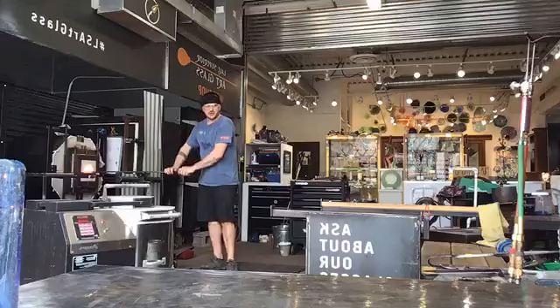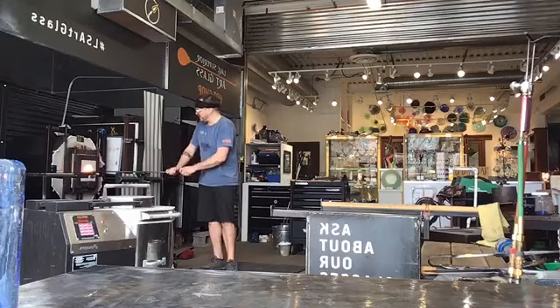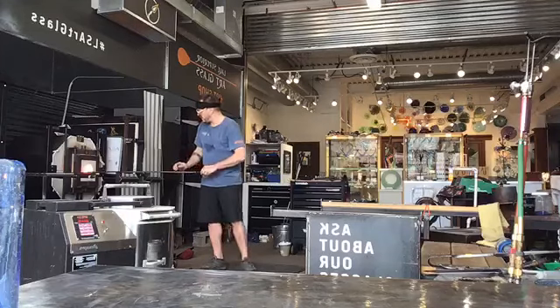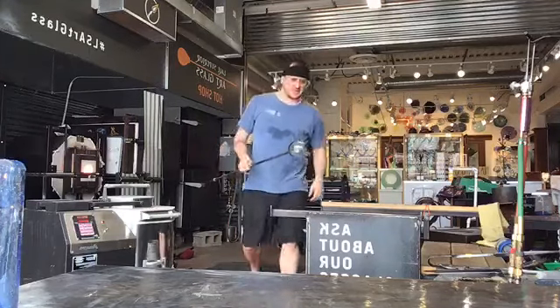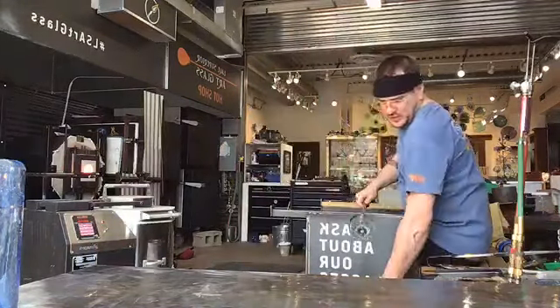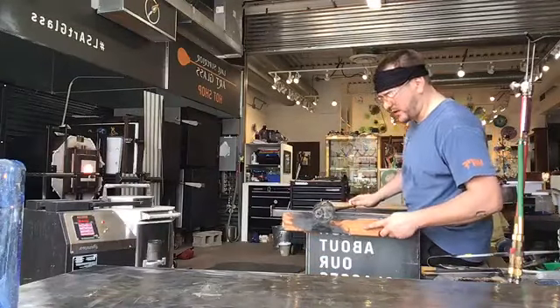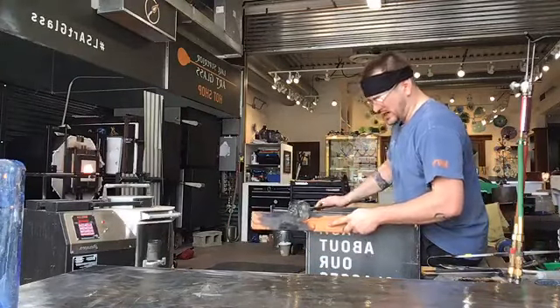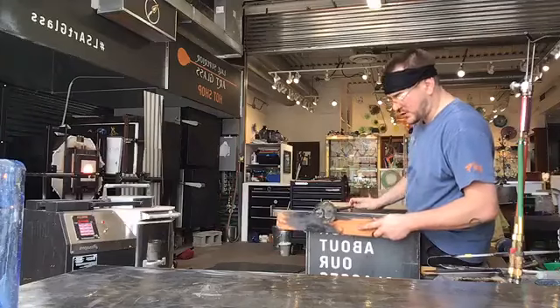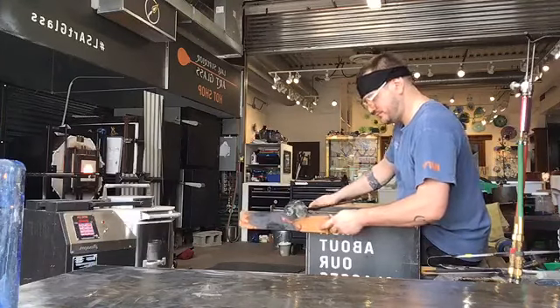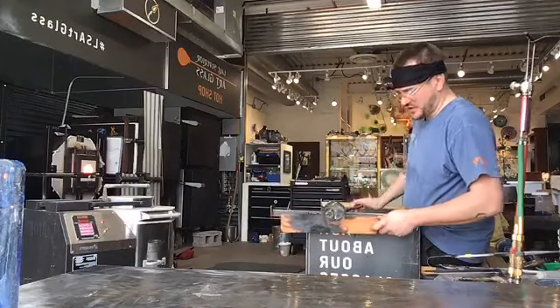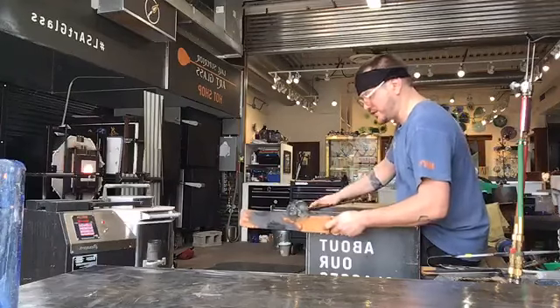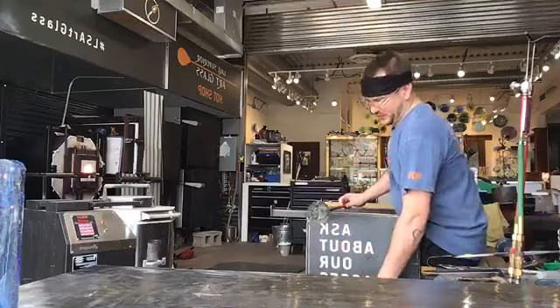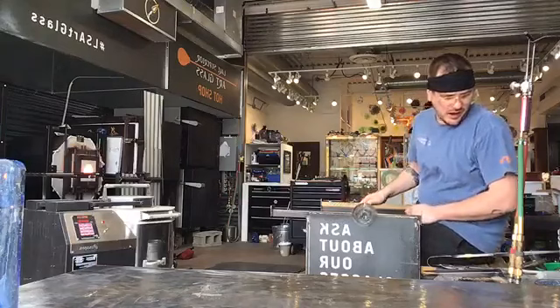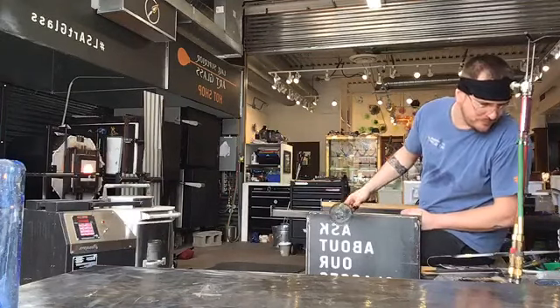So a deep flash into the glory hole, which is our reheating chamber. It's at about 2400 degrees. Our molten glass is at about 2100. So our reheating chamber is hotter than the furnace, so that as we're working, it'll reheat our glass quicker. Once again, just making sure it's flat on that punty. Looks pretty good. And I'm able to go open this up.